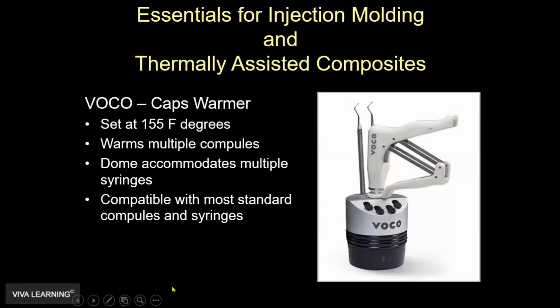If you look at the composite warmers available today, Voco has one. It's called the CAPS warmer. Here you see a schematic, a photo of it. Let's be fair. You can either go to BioClear and get a heat sink composite warmer. You can go to AdDent and get a Calset composite warmer. Voco has a very good one that has room for the composite gun, anesthetic syringes, and 4 compules. And my preference is at 155 degrees Fahrenheit.